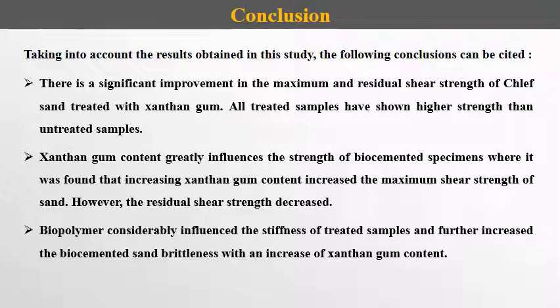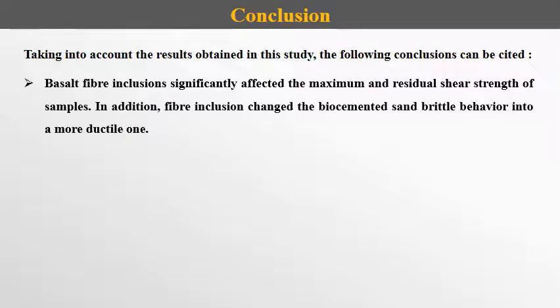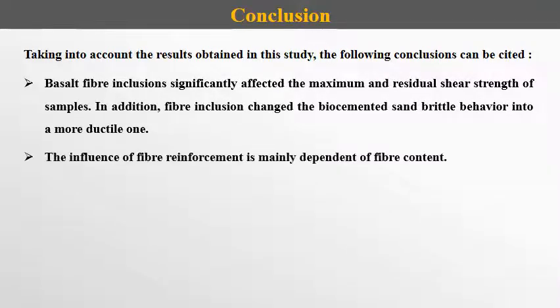Biopolymer considerably influenced the stiffness of treated samples and further increased the biocemented sand brittleness with an increase of xanthan gum content. Basalt fiber inclusion significantly affected the maximum and residual shear strength of samples. In addition, fiber inclusion changed the biocemented sand brittle behavior into a more ductile one. The influence of fiber reinforcement is mainly dependent on fiber content.